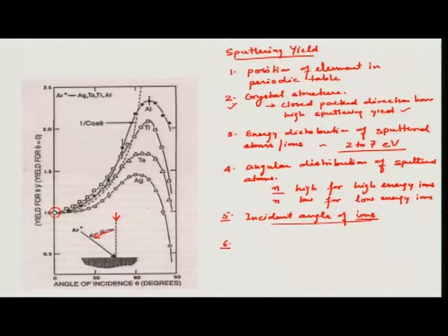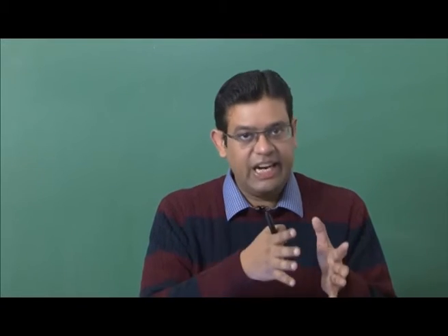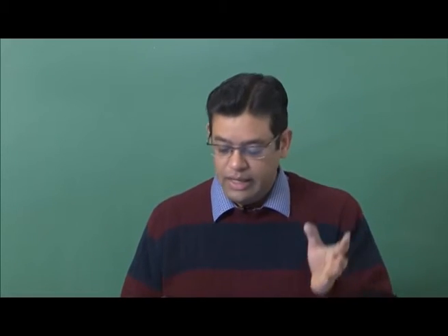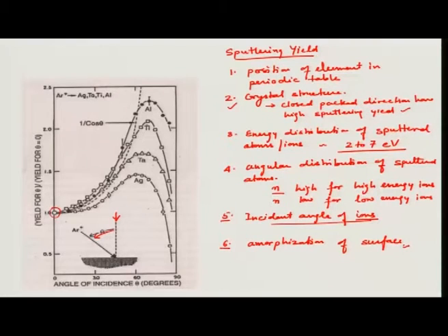So this amorphization of the surface happens during ion bombardment. Now if you have your target at a higher temperature, you would be able to anneal these defects, and the target will become polycrystalline again. So you can decide whether to work at room temperature or a higher temperature, depending on whether you need an amorphized surface for sputtering, for various depositions of different thin films.